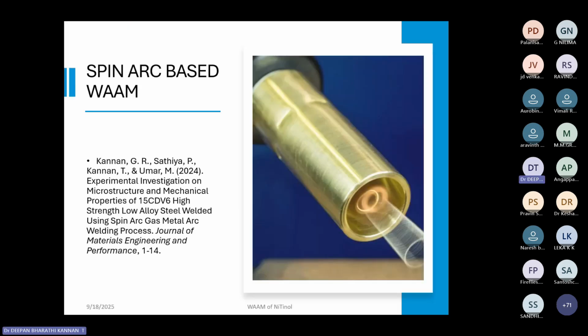Another one is the spin arc based system, where the filler wire will be rotating at a constant speed in a constant diameter. So this will also help us to build the layer at a faster rate. The molten metal deposition rate also will be on the higher side. And through literature, I found that people are using it for joining two materials. But with respect to wire arc additive manufacturing, there are limited literatures using this spin arc based MIG power source. So these are all some of the advancements that could be explored with respect to wire arc additive manufacturing of nitinol.